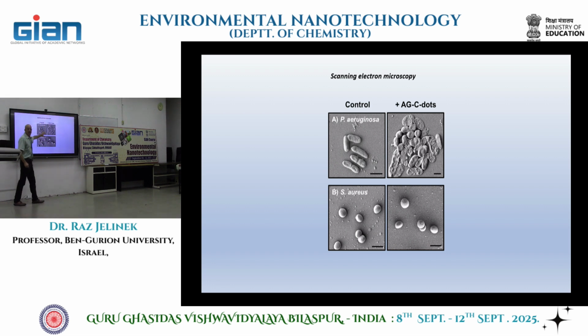So these are electron microscopy images. Okay? These are the Pseudomonas bacteria. You see the rod shape. This is control without carbon dots. Here we added the carbon dots and we waited 30 minutes. You see that all these are dead cells. Carbon dots kill the bacteria.